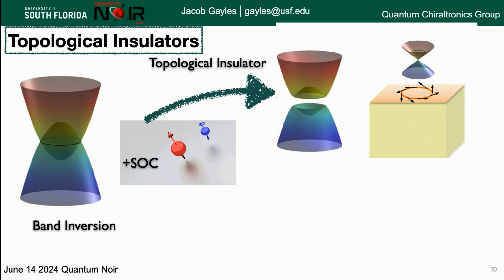And so on one end, you have what's called a topological insulator. And so this is a completely different type of material than what we had in the old days, where a bulk material or infinite material of this is completely insulating. Now, to make it topological, you have to cut this material. Once you cut this material, it's interfaced with a different material, which is vacuum, which is also insulating. But these are two different types of insulating materials. And for this perturbation to work, you need to flip the inverted bands. And in doing that, you create a metal only at the interface. So it's the same material throughout, same characteristics throughout, but only at the interface do you have this conducting band. And those conducting bands form a Dirac point.